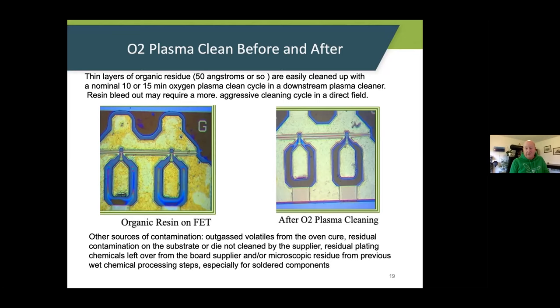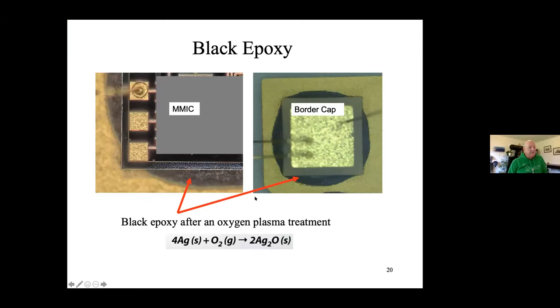Even plating, you know, if you don't clean the, Lee was talking about ENEPIG. Well, ENEPIG supposedly wire bondable and solderable, but it takes a lot of work to get good at wire bonding the ENEPIG. And one of the issues is cleanliness coming in the door from residual plating solutions. And you know what really cleans that up? Like, unbelievable, is just a good oxygen plasma treatment. So, or if you do any kind of soldering. So there's a role for oxygen plasma.